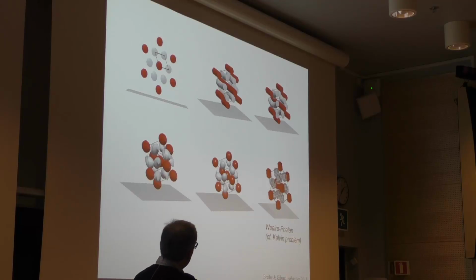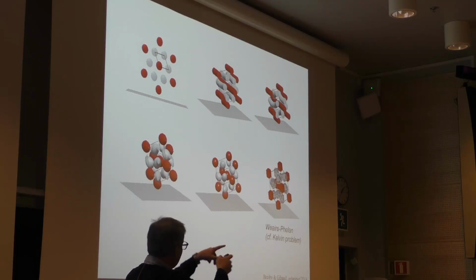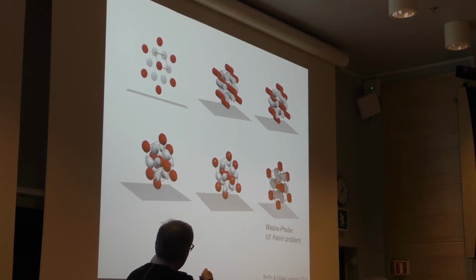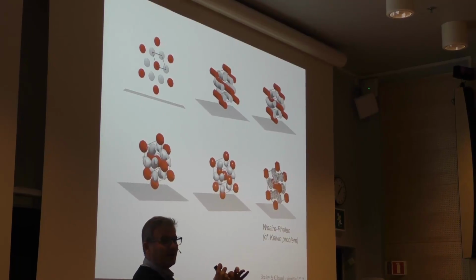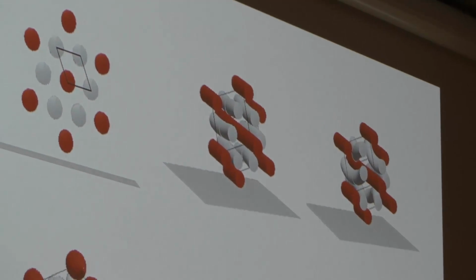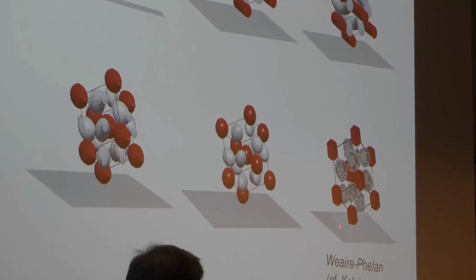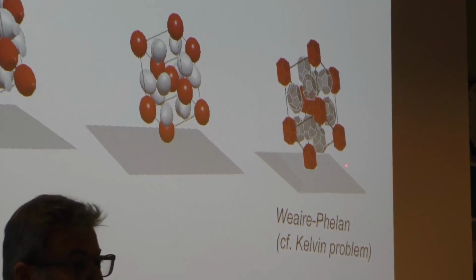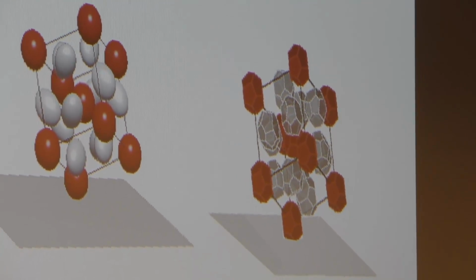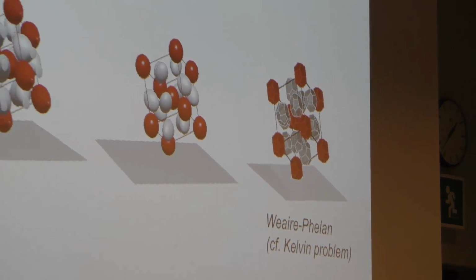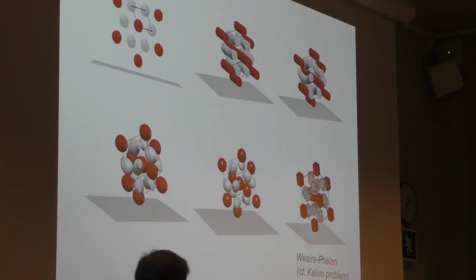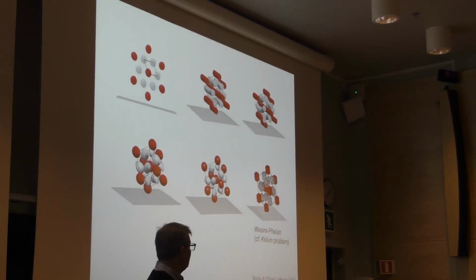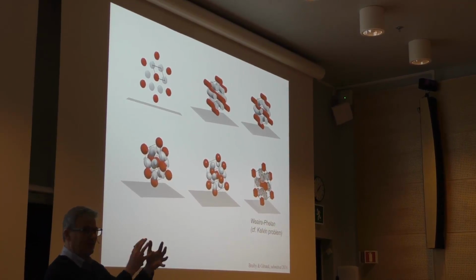Then they start to curl up a little bit. So this is a perspective drawing. We just see them from a slightly different angle. The difference between what I have shown in red and gray here is just meant to illustrate that these are in different symmetric positions in the final structure. So these gradually curve up and break into smaller units, and it turns out that in the very end it can be described by the so-called Weaire-Phelan structure that some of you have maybe heard about. It relates to the Kelvin problem of how you can partition space into equally sized units with the least border area, right?